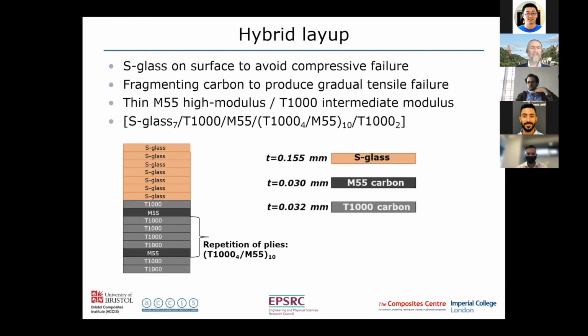So initially we did this with unidirectional material. We use the same S-glass material as before, but now we've got a carbon hybrid, and essentially it's layers of M55 high modulus fibre sandwiched between pairs of T1000 intermediate modulus, which have a higher tensile strain to failure. And layups here, so we have a number of 10 repeating blocks of M55 between the T1000 and 7 layers of full thickness glass.